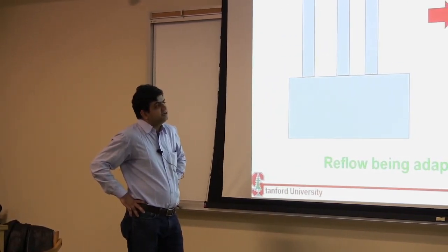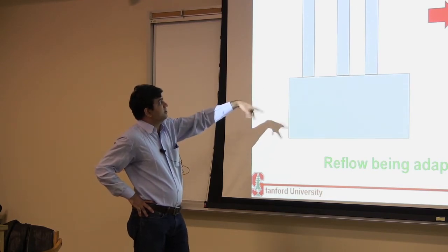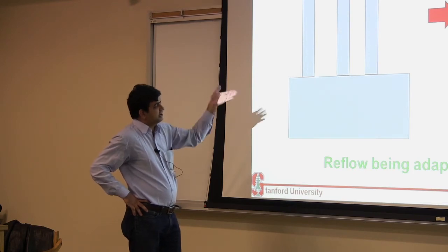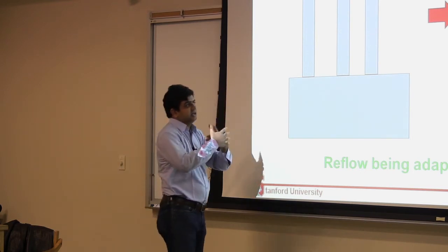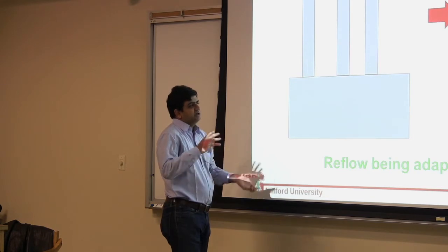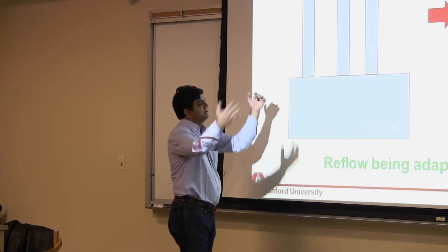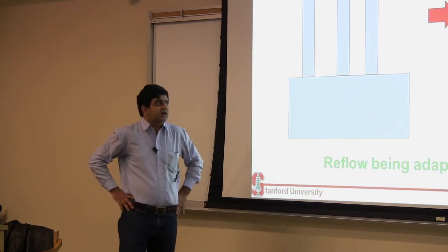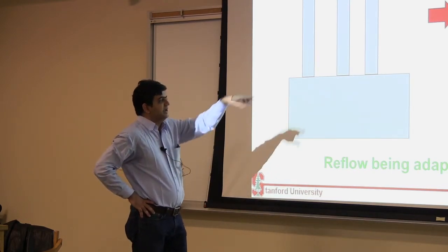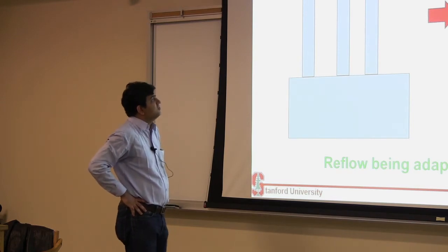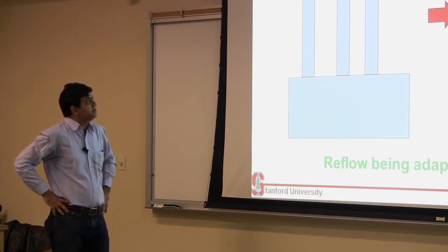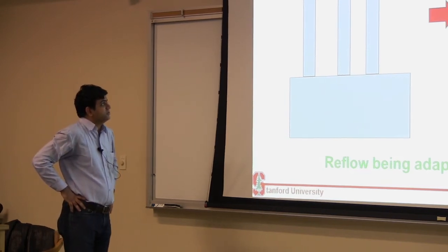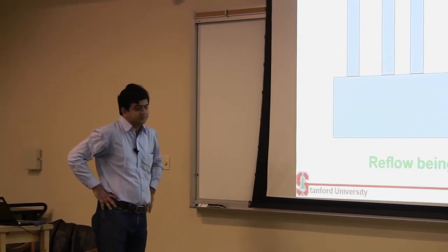This is not just limited to copper. For dielectrics, say you have an STI trench and you want to fill it up with dielectric, you deposit these dielectrics in a state between being a liquid and a solid, and they essentially flow into it, and this capillary force pulls that layer into your high aspect ratio structure. Again, a very cool technique. This is something which just scales beautifully as you go to even higher aspect ratios.